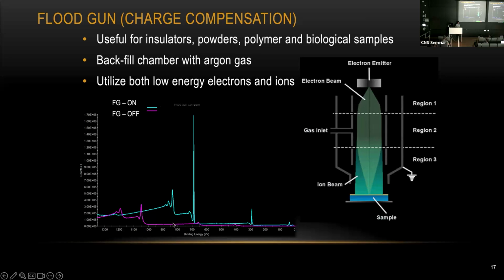So when your sample has some charging going on, your entire spectrum is going to shift to a higher binding energy. So it will be very difficult for you to determine which peak belongs to which element. For instance, right in the middle here, this high peak actually belongs to fluorine. But now you can see from the measurement without the flood gun, we can't even see the fluorine peak here, and it also becomes much broader. So that's why without any flood gun for insulating samples, you are not going to get any good data at all.